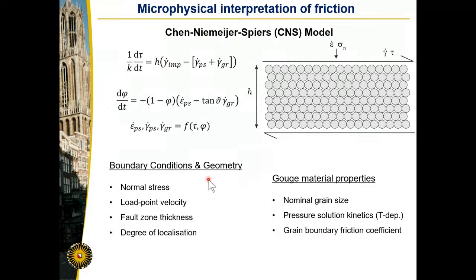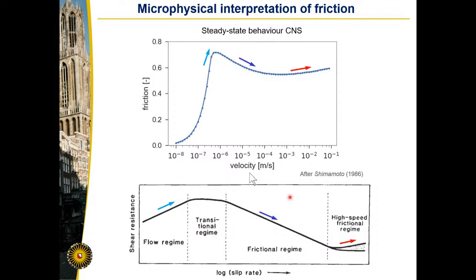Now, I won't go into detail, but you can couple these equations based on this microstructure, and then you can use the boundary conditions and the geometry of the microstructure to predict what the frictional strength of your gouge layer is, based on the competition between this time-dependent mechanism and the slip-dependent mechanism. And all we need to put in is the kinetics of dissolution, diffusion, and precipitation. And that predicts a profile that looks like this.